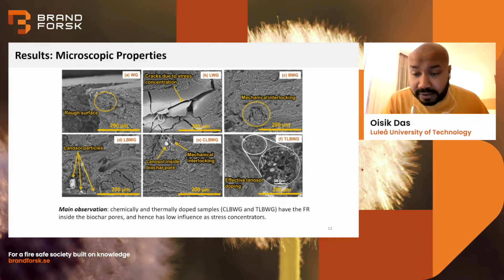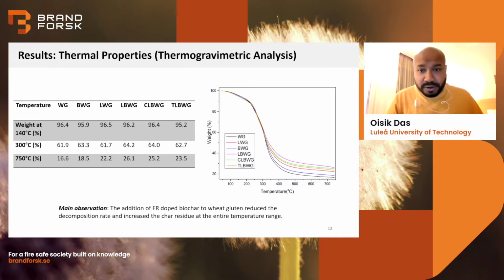However, if we look at number F, we can see that the biochar is properly manifested with the fire retardant doped inside the pores. We have a magnified view. This is what we have tried to do in the project, that the fire retardant particles are doped inside the biochar and not present on the surface, so that they can still function as fire retardant without reducing the mechanical properties. Moving forward, this is where Rodha will take over.